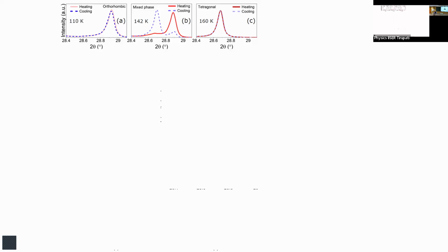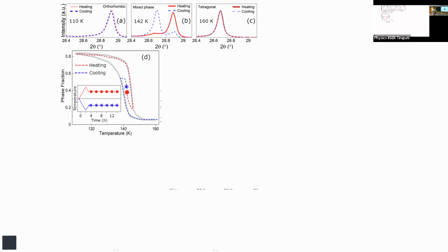But the temperature dependence differs on heating or cooling. This is the orthorhombic peak, and this is the tetragonal. The intensity is completely different depending on which path I came by. And since the photoluminescence signal of this phase and that phase are different, the photoluminescence intensity depends on the history. And that's why I can know the history. Though you cheat me by bringing the temperature back, it leaves an indelible mark on the photoluminescent signal for me to detect that actually there was a breach, that you had broken out. And all the experiments that I showed you with photoluminescence can be reproduced with X-ray diffraction.